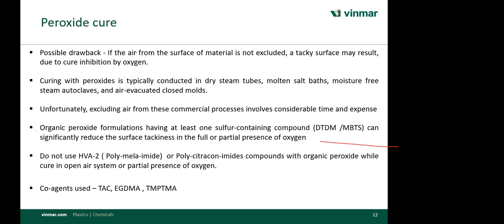avoiding oxygen from the system is very, very difficult and very challenging. If you wrap the compound itself, say you want to make some product by molding, you make the sheet, wrapping it in a plastic sheet. Once you open it, again it is coming in touch with the air, again in contact with some moisture. So there is a chance of oxygen entrapment in the system. So there please try to avoid HVA-2 type of coagent. All other coagents will give you a very good peroxide system if you use some sort of DTDM or MBTS at the 1 to 2 PHR level.